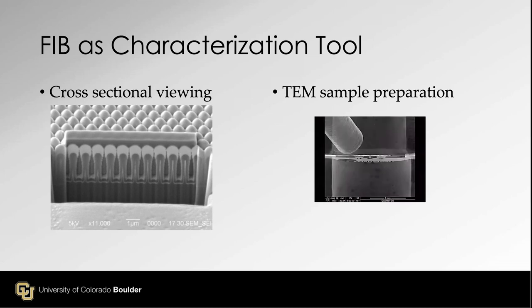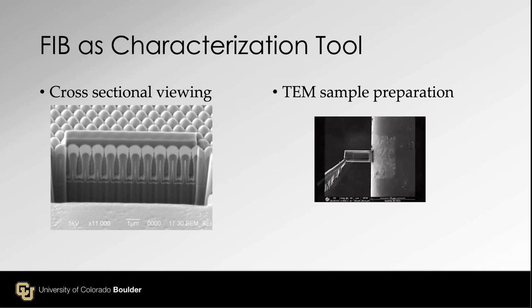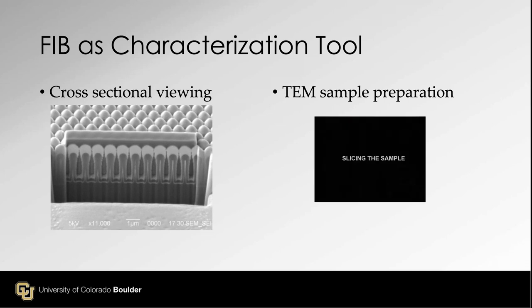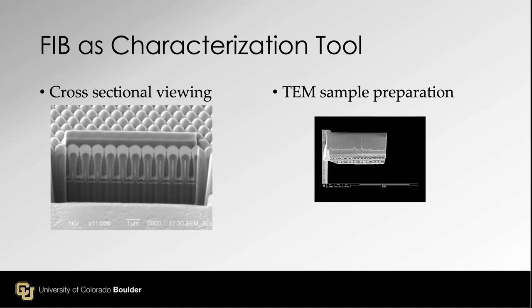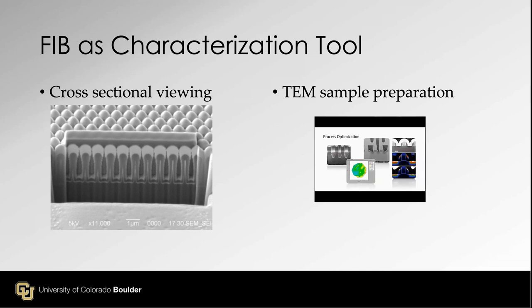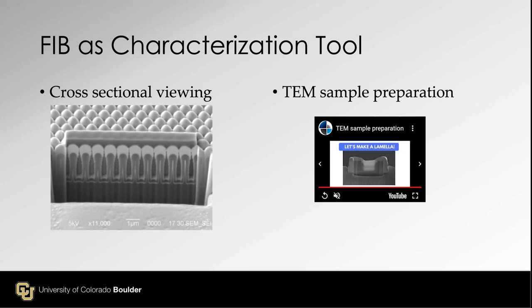Then you can mount this tiny slab onto the TEM half grid. You can connect and detach the microprobe. Then you have to make this slab thinner, thin enough, suitable for TEM observation, which is 100 nanometers or 10 nanometers, depending on what you want to do. So this process is useful for optimization, defect analysis, tool qualification, or failure analysis. So for site-specific TEM sample preparation, FIB is a must-have tool. The semiconductor industry uses FIB a lot for this purpose.